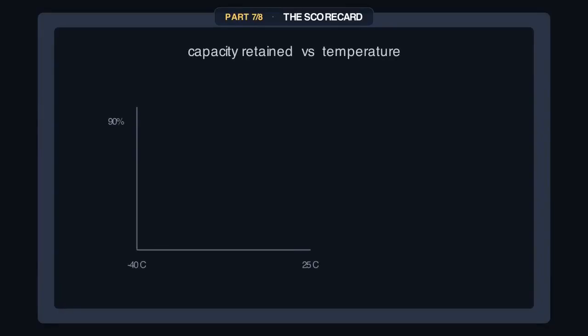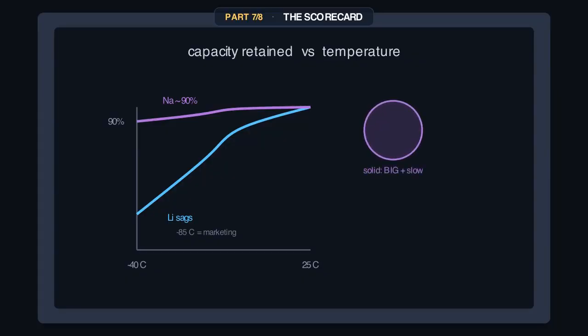Watch capacity as the temperature drops. Lithium sags hard below freezing. Sodium holds roughly 90% of its capacity at minus 40 degrees. And a quick honesty flag: you'll see vendors shout minus 85. Treat that as marketing. Minus 40 is the defensible number, and it's remarkable enough.